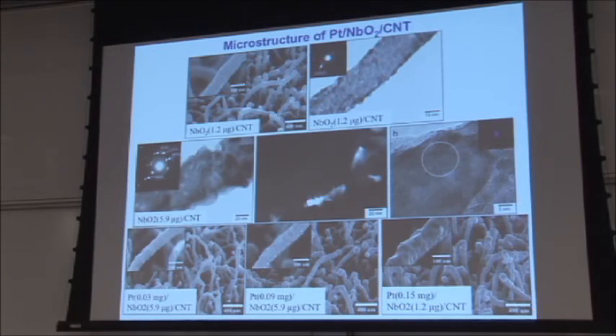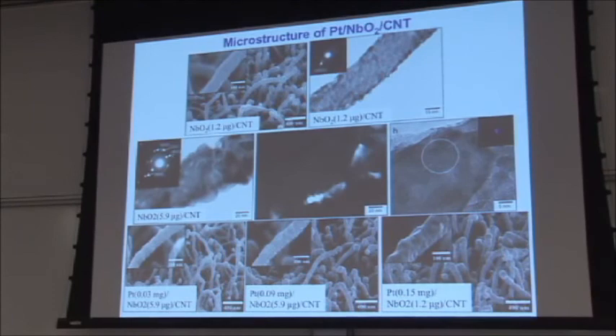So essentially, when you're imaging them, they look very large. They certainly look larger than 1 nanometer, but that's because you're imaging their maximum dimensions. They're actually quite thin, normal to their surface. And the wetting is almost complete. There's some little regions where you don't have niobium oxide wetting, but you could actually, again, see the carbon nanotube through the niobium oxide. And again, even with a thin layer, you had very good wetting of niobium oxide. And again, as you expect, because there's chemical interaction between niobium and the platinum. There's a strong chemical interaction even when it's an oxide.